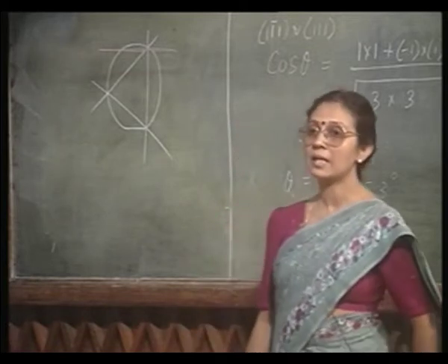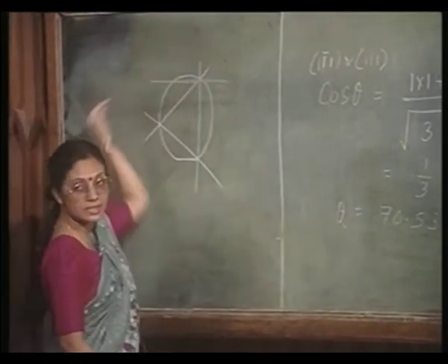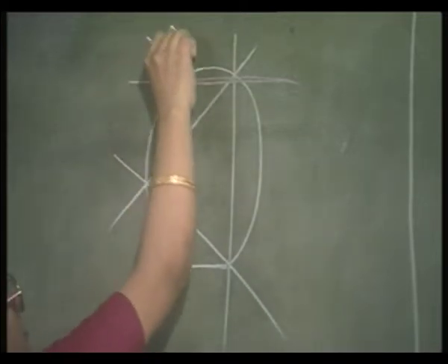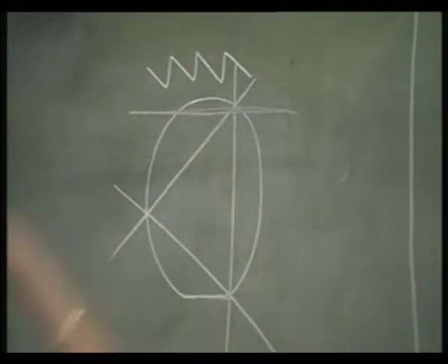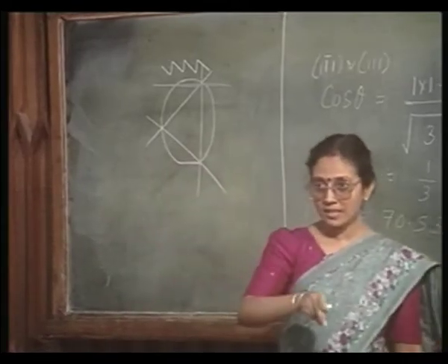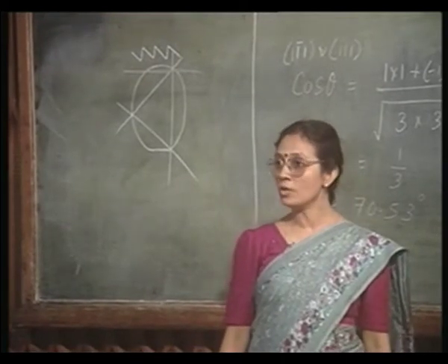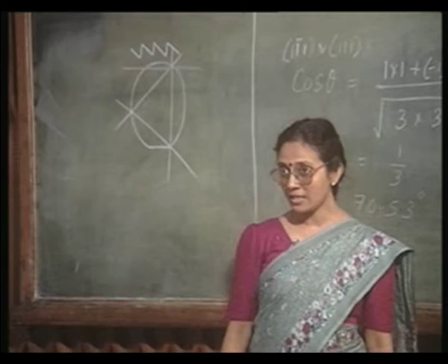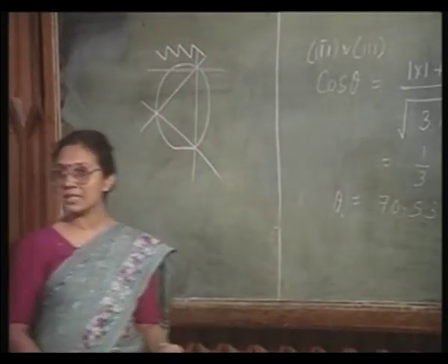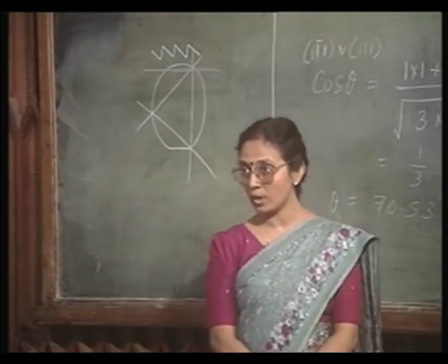Okay. So, what I will have is not a clean break along this line, instead I will have a zigzag cut with each zig and each zag along the 110 directions, right. So, you will find that along this direction it is breaking cleanly, because it is cleaving along a natural direction of 110.